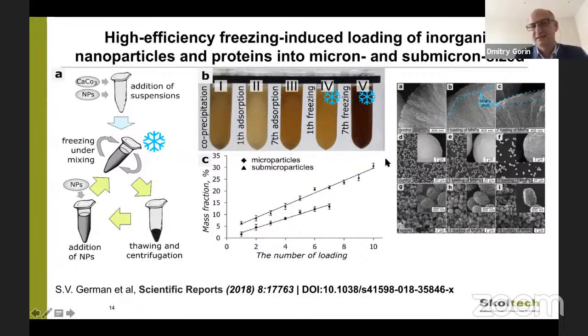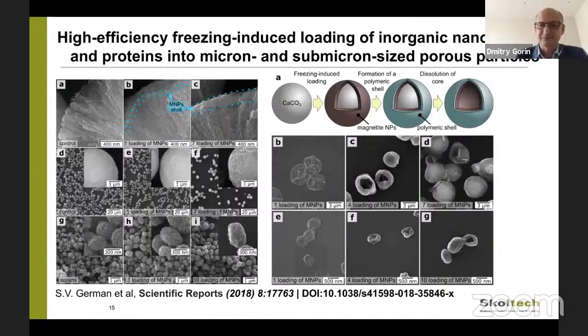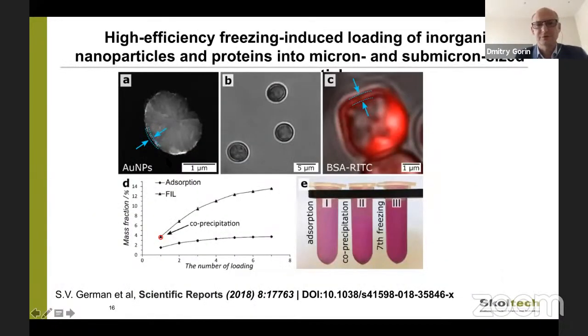Fortunately, we have obtained a linear dependence of loading numbers for microparticles and for submicron particles. And of course it's not a universal approach, but we can apply it not only for preparation of core-shell structures, but also for preparation of shell-only structures. This means that we can dissolve the core and obtain a freestanding structure. This approach we can also apply for loading gold nanoparticles and proteins like albumin. And our colleagues have already used this method for loading DNA or RNA, and it's working very well.